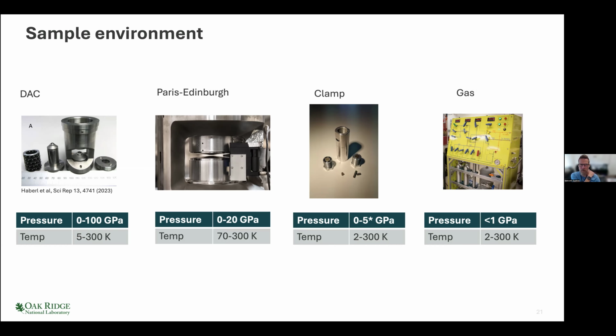Of course, we have Paris Edinburgh cells, which is a very traditional way to do high pressure neutron diffraction. These can get up to about 20 GPa, and we can run them at low temperature. We're in the process of thinking about elevating the temperature. And then we have the really traditional gas and clamp cells, which are available. Although again, with these, there are some specialities. Typically, a clamp cell will not go above 2 GPa, but we have a special one created again by Reini, which has been demonstrated up to 5 GPa.